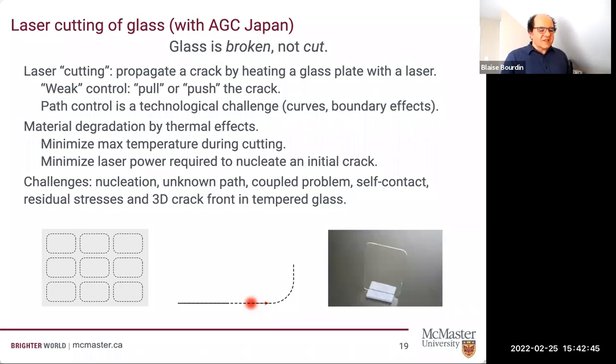So we've applied that to many other problems. One problem that I really like is the problem of laser cutting of glass. That was a collaboration with a glassmaker in Japan. And the idea is, if you think of it as an example of where fracture is important, is not a bad thing, is that nobody knows how to cut glass. We know how to melt it and we know how to break it. And typically, the way you cut glass is you do controlled fracture. So you can score and break, but scoring and breaking is great for rectangles. But you know, this is not a rectangle of glass. So if you want to do something like that, you need a better method.